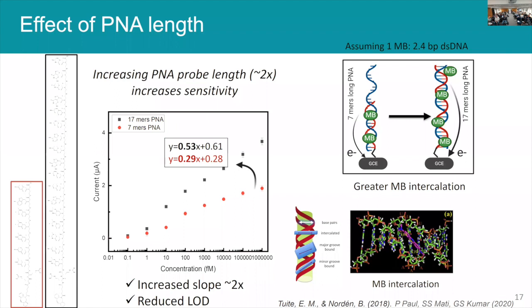So the only way that we are detecting current, the only way that we're detecting electrons at the surface of this electrode and this redox reaction, is if this electron transport is mediated through the duplex itself, right? And this is really cool because a lot of previous research has shown that this pi stack in the duplexes can mediate electron transport through it very, very efficiently. And I think that's what we're seeing, which is really cool.